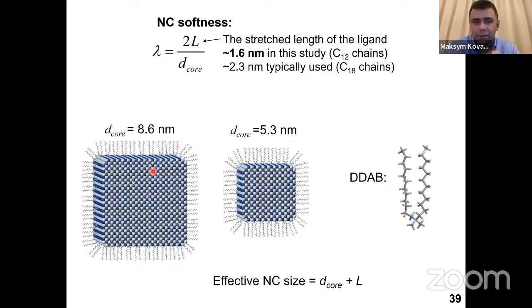So to minimize the softness, we actually stick to the ligand which is shortest of all, which can still provide colloidal stability, which is the one I already showed you in some of the previous slides. And then we took two kinds of cubes. One is the bigger one, which is harder, and the smaller one, which is softer. So the effective size of the cube is the core plus the ligand length.